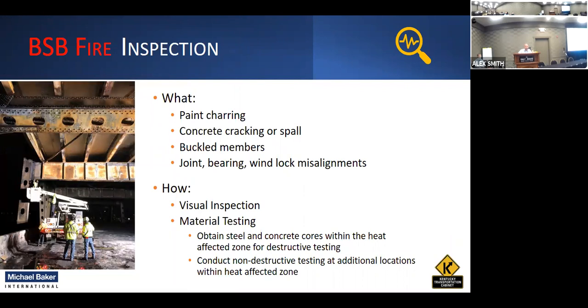So from the inspection standpoint, of course, what were we looking for? Paint showing from the heat, from the fire, concrete, buckled members, and of course, joints, bearings, and wind locks, and that kind of stuff. So primarily a visual inspection, but then we did incorporate material testing that we'll get into here in a bit. So we did obtain steel core coupons, concrete cores of the deck within the heat affected zone, and also non-destructive testing at additional locations within the heat affected zone, and also control samples outside the heat affected zone. We took core samples of steel and concrete to get a baseline of what that was. I think Jason will get into that here a little bit.